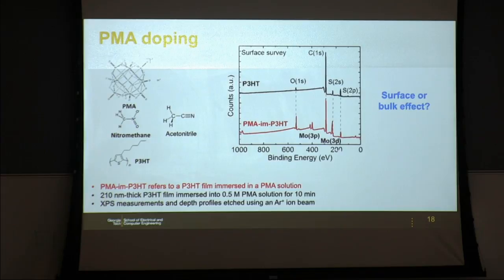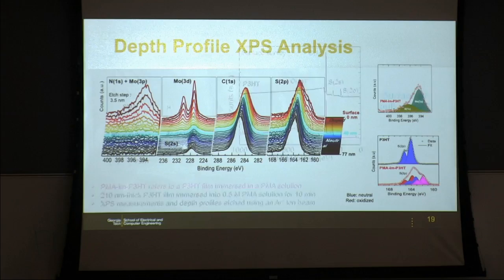But the question is, is that just a surface effect or is it a bulk effect? And so what you can do is you can start etching the film, and then after you've removed a thin layer, you repeat the experiment, and so you can follow the composition of these atoms or produce kind of a profile, a concentration profile of these atoms in the film.